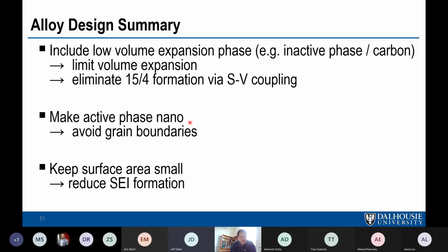You want to make the active phase nano to avoid grain boundaries, which can be sources of fracture within the particle. And you want to keep the surface area small to reduce SEI formation, or I guess a better way to phrase it is keep the surface area that's exposed to the electrolyte small. So that could be done, in the case of SiO, with big smooth particles that have a low surface area, or by embedding the alloy within graphite so you don't have surface in contact with the electrolyte at all.